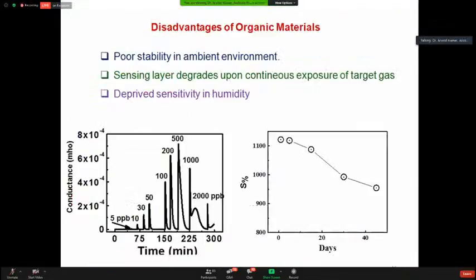But they suffer many disadvantages. For example, they show poor stability in ambient condition. Second, the sensing layer degrades upon continuous exposure to target gases, and their sensitivity is reduced in humid conditions. In this graph, it is clear that if we continuously expose this sensor to the target gas, here chlorine gas, after some concentration the sensitivity degrades. You can see that for 2000 ppb, the sensitivity is less as compared to 500 and 1000. So stability is the issue.